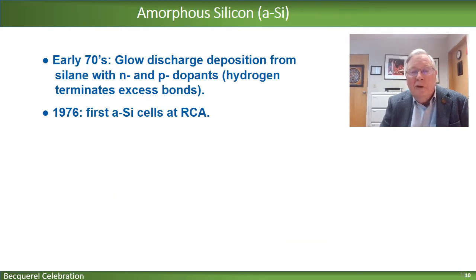So as far as amorphous silicon is concerned, this got going in the early 70s, where the silane material, which obviously has silicon in it, was subjected to a glow discharge, with additional dopants of either N or P-type material, and with hydrogen to terminate the excess bonds, reasonably good material was produced. And in 1976, the first amorphous silicon cells were made at RCA in the US.